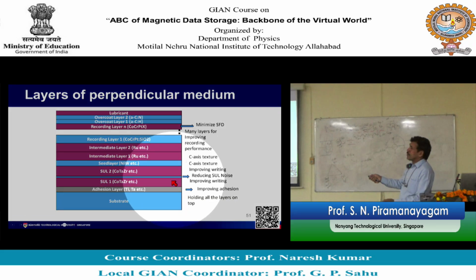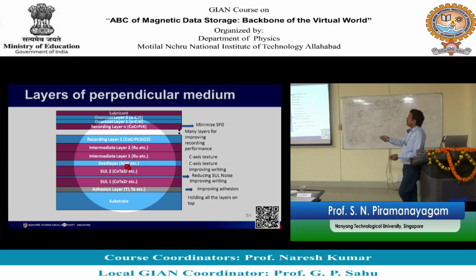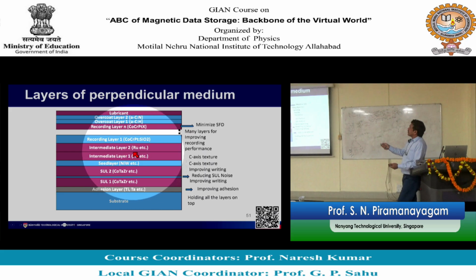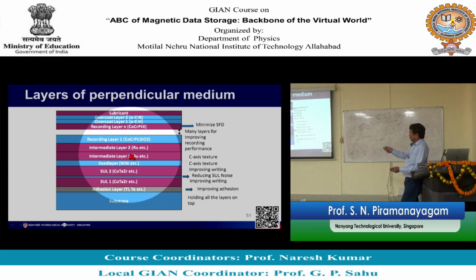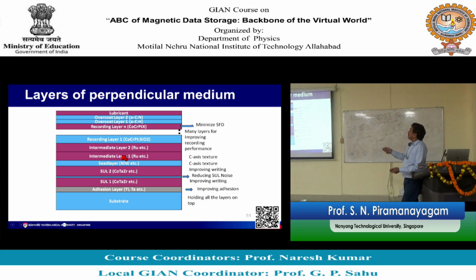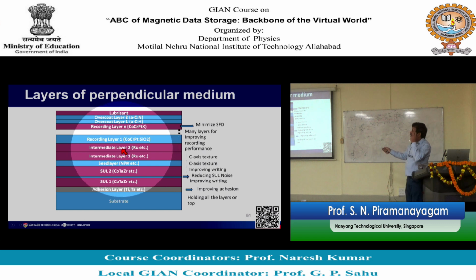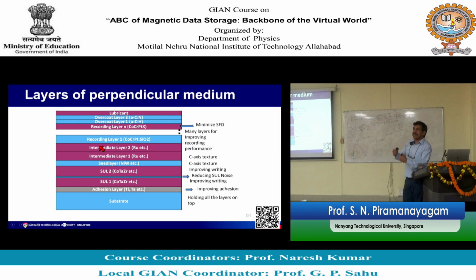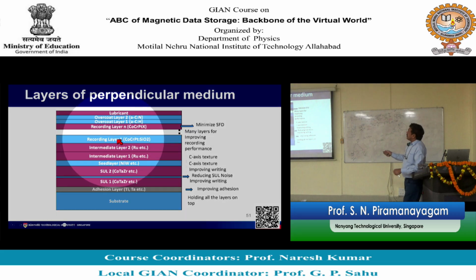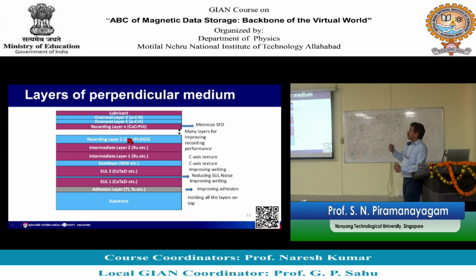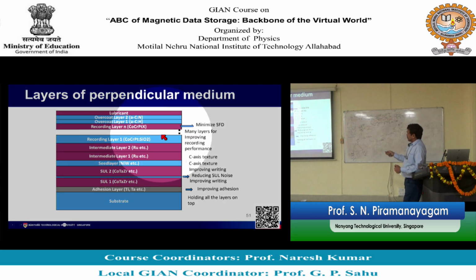Then we talked about the seed layer. The seed layer helps to achieve C axis orientation for ruthenium, and we need 2 ruthenium layers because this gives rise to good C axis texture, and this layer is sputtered at high pressure. It helps to segregate the grains, and the recording layer also is sputtered at high pressure, so that the grains are segregated from each other, and we use many layers to improve the writing performance.